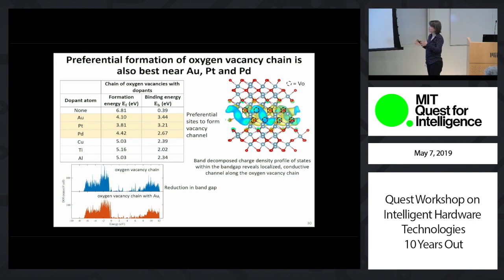And ultimately, the increased conductance is introduced from the accumulation of these oxygen vacancies. So when you have an oxygen vacancy chain, you have plenty of in-gap states which not just reduce, but almost make that zone metallic-like. Okay?